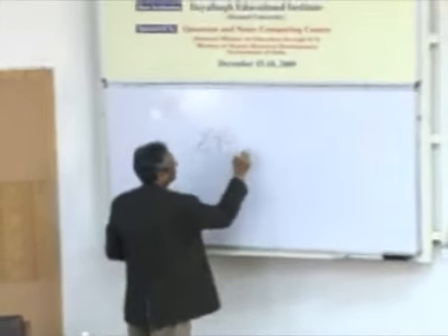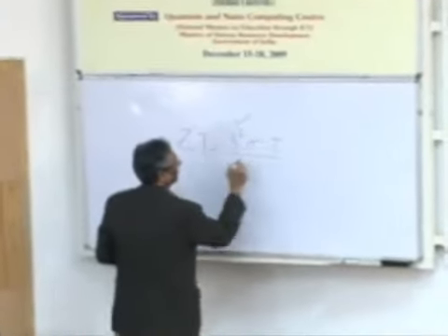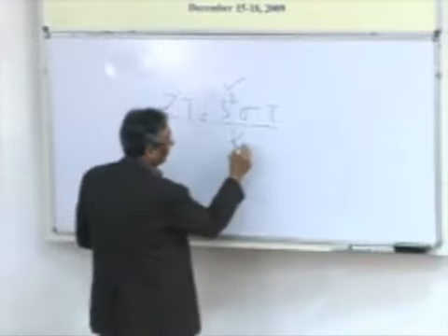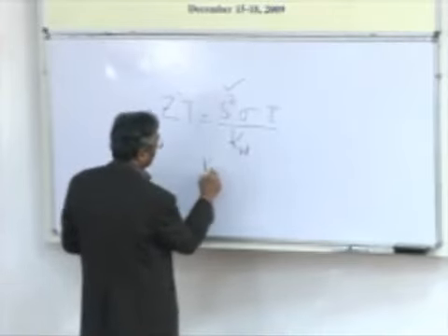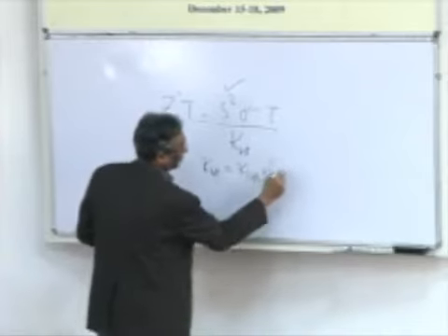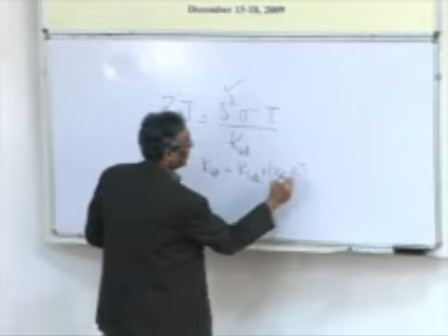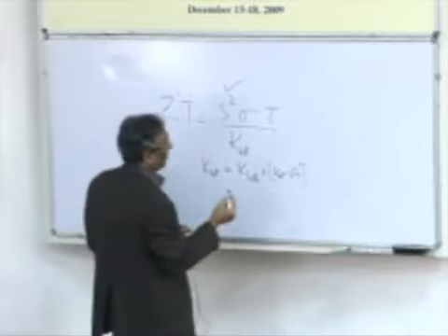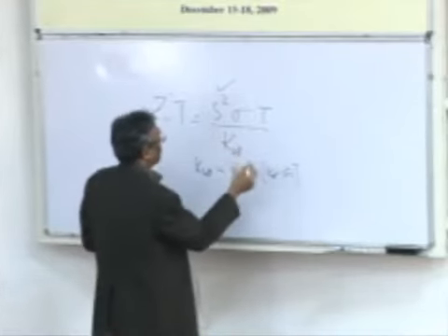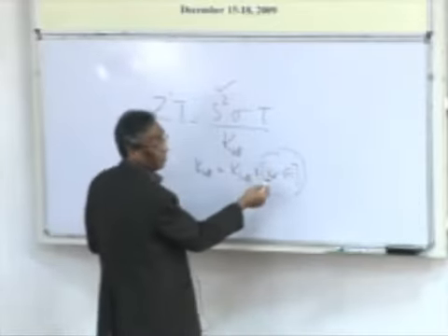Is that really possible? Has this been experimentally realized? No, experimentally not realized. Unfortunately, in experiment, when you measure ZT, S squared you can measure, sigma you measure, T you measure, then here is kappa. Unfortunately, thermal conductivity doesn't care whether you're getting it from electrons and so on, you measure the total. So it's the phonon, the lattice, plus k electron minus S squared sigma T. I measure both, so I don't know how to do it experimentally. But one way is to inject some theory, or do the following, which people do, which is not quite right. They simply use some old rules called Wiedemann-Franz, which breaks down really dramatically in this limit.